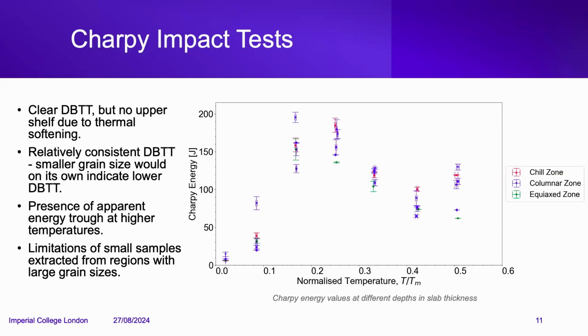And interestingly, the ductile to brittle transition temperature for each of the solidification zones was relatively similar. You would expect the columnar zones, which have much larger grains than the chill zone, to have higher brittle to ductile transition temperatures. But there's clearly another mechanism in effect here because they are relatively consistent. Now, the actual temperature values have been normalized. Apologies, because they are proprietary information of Tata Steel.